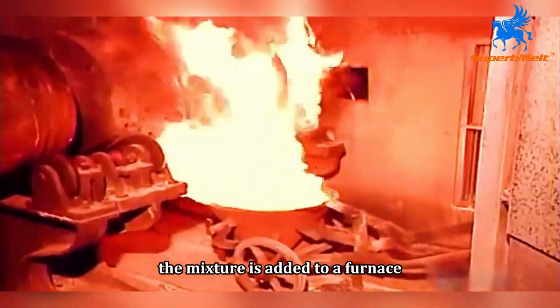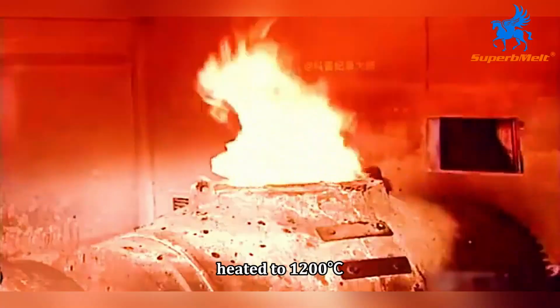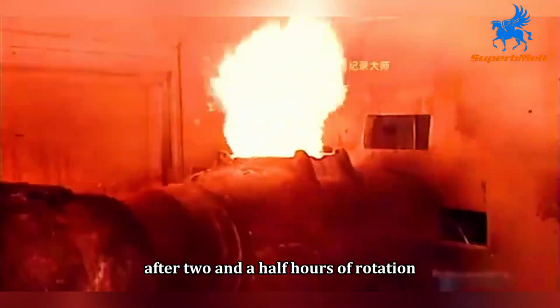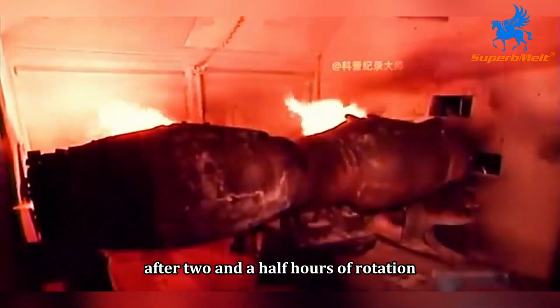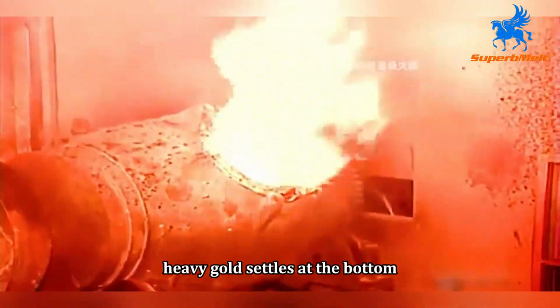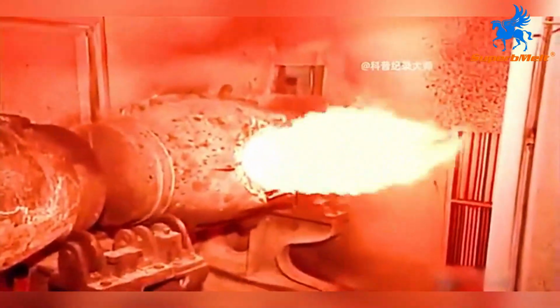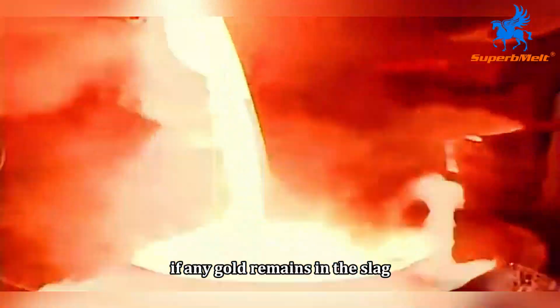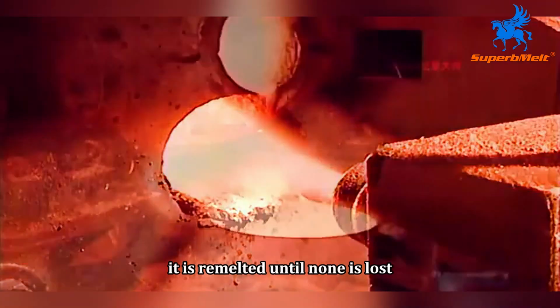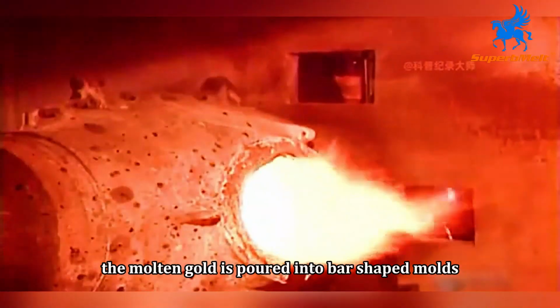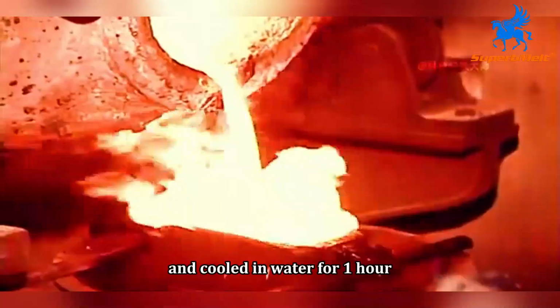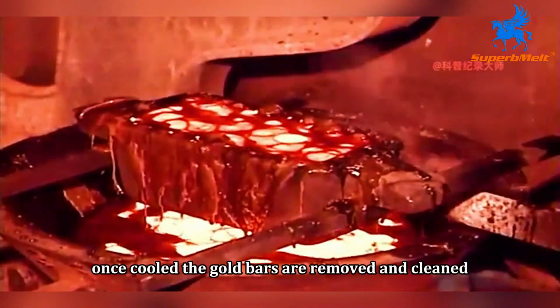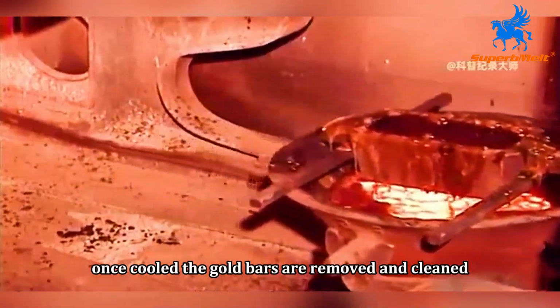The mixture is added to a furnace heated to 1,200 degrees Celsius. After 2.5 hours of rotation, heavy gold settles at the bottom while slag floats to the top. If any gold remains in the slag, it is remelted until none is lost. The molten gold is poured into bar-shaped molds and cooled in water for 1 hour. Once cooled, the gold bars are removed and cleaned.